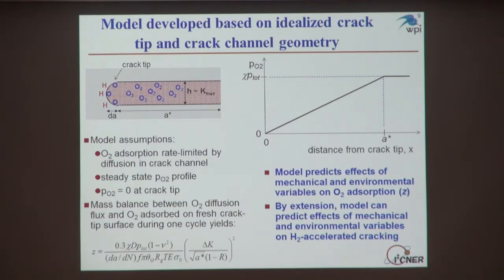This is really, I think, the foundation of the model. And so in order to describe this diffusion, we're going to assume a steady state oxygen profile down this crack. And so here's just an illustration of a potential oxygen profile down this crack channel. And we're also going to assume that the oxygen concentration or the oxygen partial pressure is 0 at the crack tip. And so this is our presumed oxygen profile.